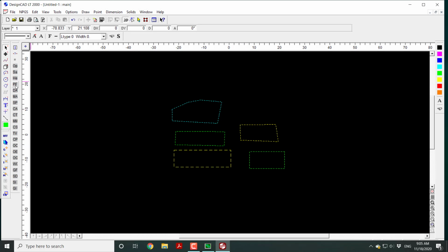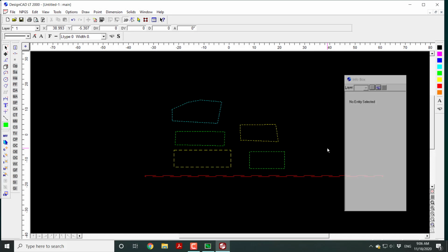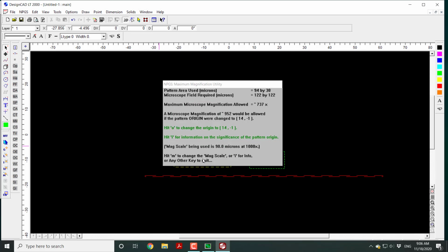For example, I could create very fine lines. This way, I create a line that is only around 500 nanometers or 460 nanometers. Because of the proximity effect, this line is going to have a much higher dose as compared with this big block. So in order to have both showing, for this one, let's say I'm using a higher dose, a different dose like this.